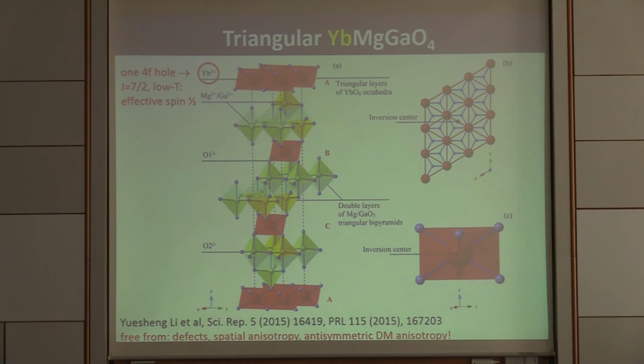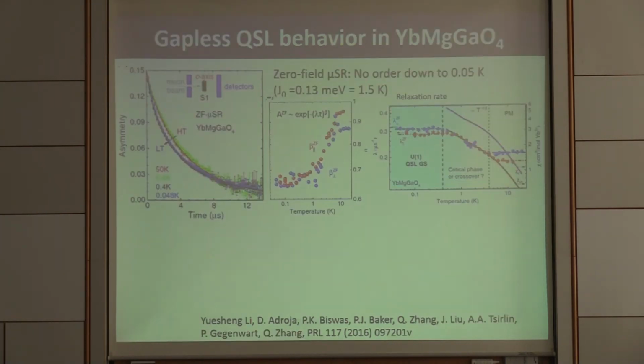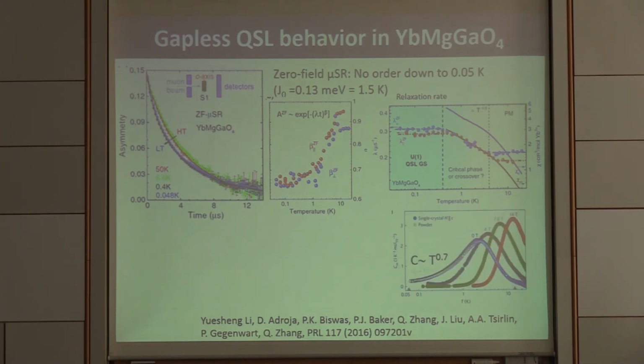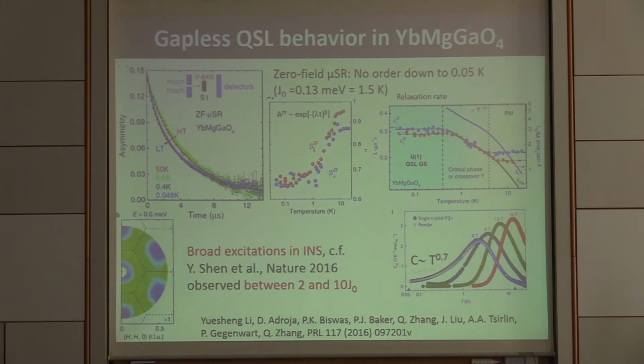And this material is nice because there is a non-distorted triangular lattice. The ytterbium has inversion symmetry, and it's well separated from the intervening layers, and there is no site mixing between magnetic and non-magnetic sites. The μSR experiments again show evidence for the absence of magnetic order and absence of spin freezing down to very low temperatures. And heat capacity, for instance, shows a power law behavior down to 50 millikelvin.